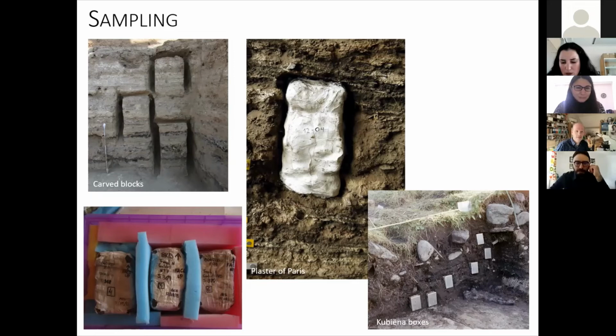Another important aspect to bear in mind is sample packing and transportation. I tend to cut holes in the corners of my sample so that the sediment can breathe, and you don't have too much moisture trapped in that can lead to microbial development and stuff. And then I place the blocks in stiff plastic boxes that are conveniently cushioned with spongy materials.